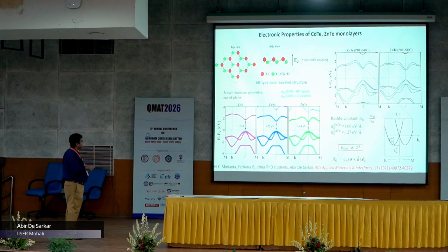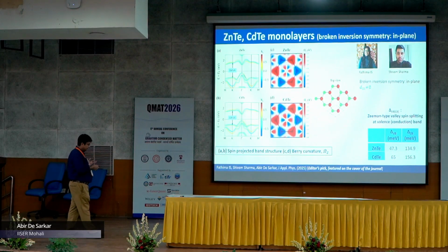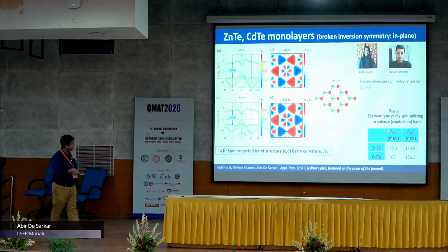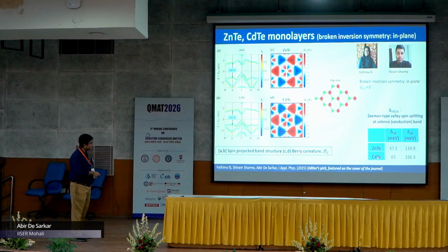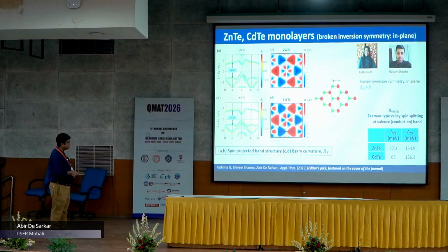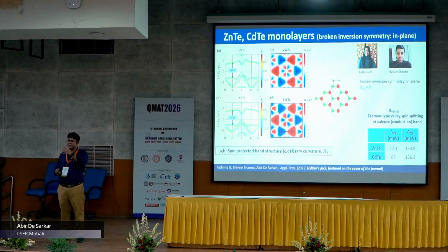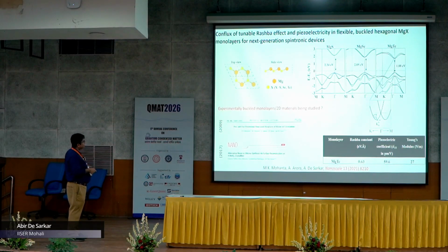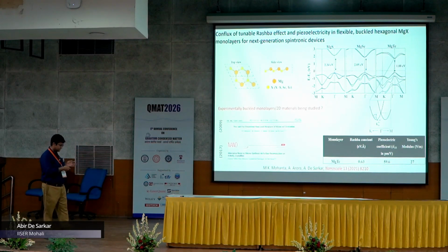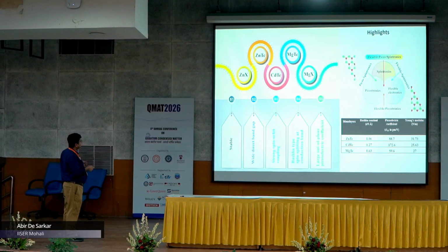And also, since the inversion symmetry is broken along the z direction, it also shows out of plane piezoelectricity. And as the inversion symmetry is broken in the xy plane of this monolayer, it shows in plane piezoelectricity and also valley polarization, and the extent of the Zeeman type valley spin splitting is higher in cadmium telluride, because cadmium is heavier than zinc. So, the CdTe monolayers also show nonlinear valley Hall effects. This is for the experts in the audience, and the same also applies to the MgTe monolayers, which are also stable.